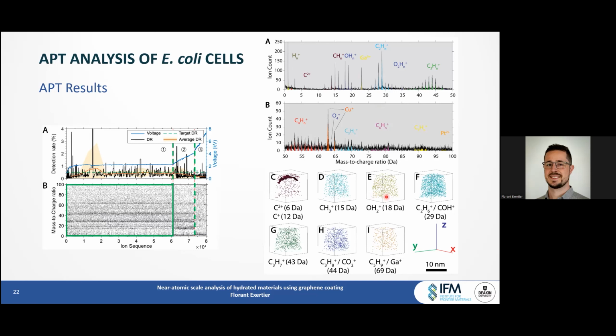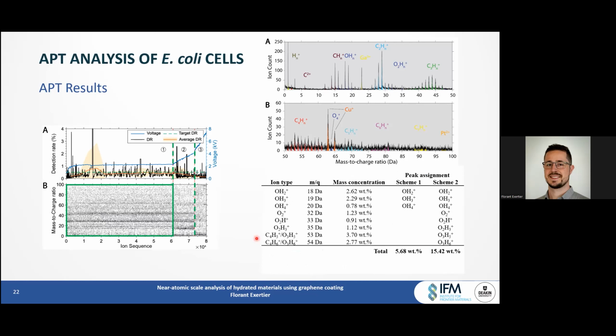So although no significant structural information, unfortunately, as can be seen in those reconstructions, was identified, the partial rehydration of the cell was confirmed. And the amount of water was estimated between 5 and 15%, depending on the peak assignment scheme. But this was the first time a hydrated cell was analyzed in this fashion.